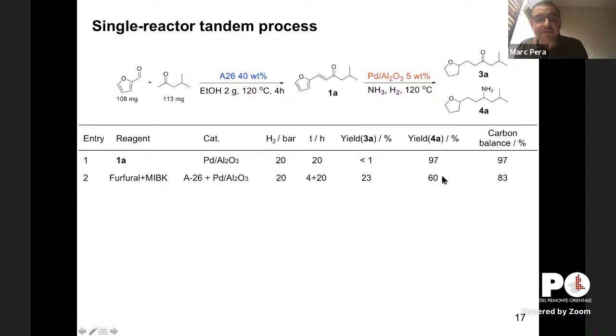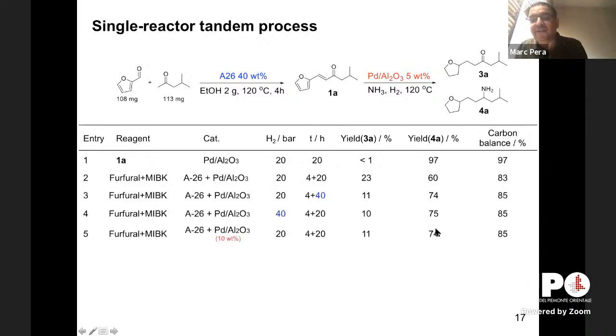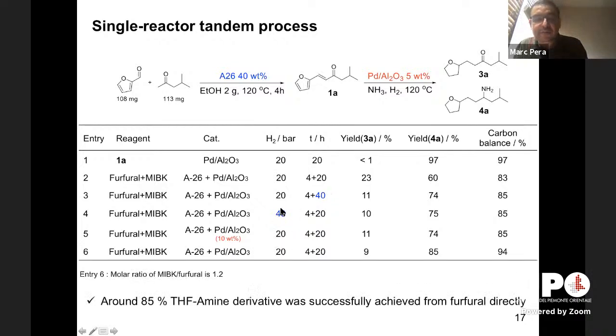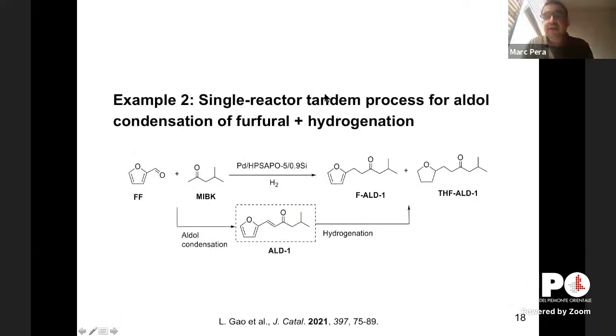When we do this, in the first experiment we just start with the intermediate, and we have 97% yield. Now in a single reactor, Amberlyst 26 and palladium, the yield is 60%. Let's optimize the conditions a little bit. We can move now to 74 by playing with the amount of palladium, the time and the hydrogen pressure. And now if we really optimize the system, especially the MIBK to furfural ratio to 1.2, the yield is excellent, 85%. So yes, we can integrate all the elements in the same reactor. We can run them in a single one pot. So we don't need to separate this aldol intermediate in our process.